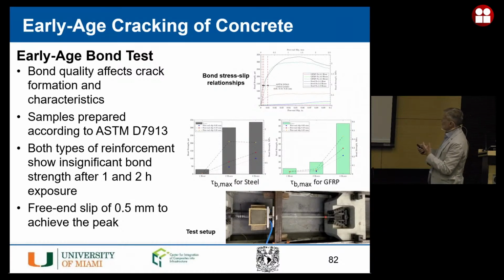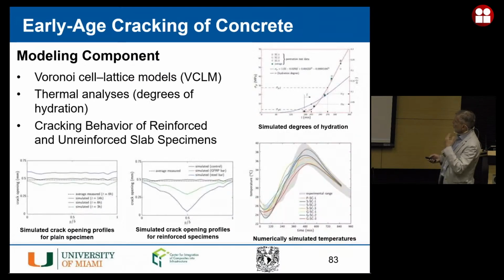In order for us to understand the reason why of this performance during the plastic shrinkage, we run these tests that we call early age bond tests. And you can see it's very similar to a pull-out test that you do according to the standard, but obviously the concrete has not yet hardened. The concrete has not gone through the full hydration process, and so you determine the capacity of the bond and you determine that you really don't have any bond, and therefore if you don't have any bond, the reinforcement is there for nothing.